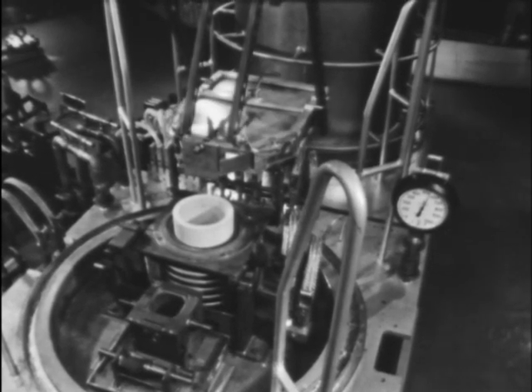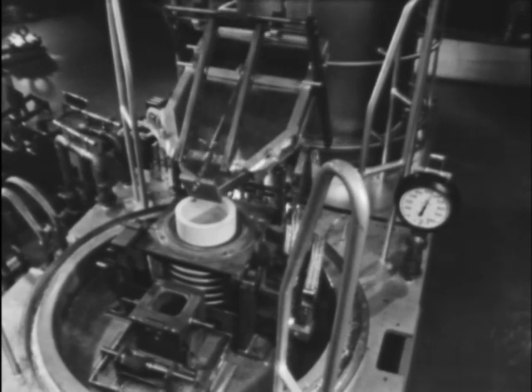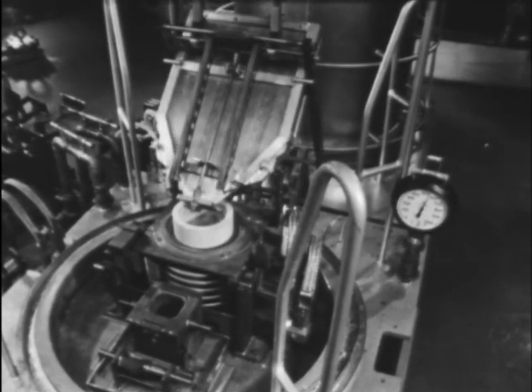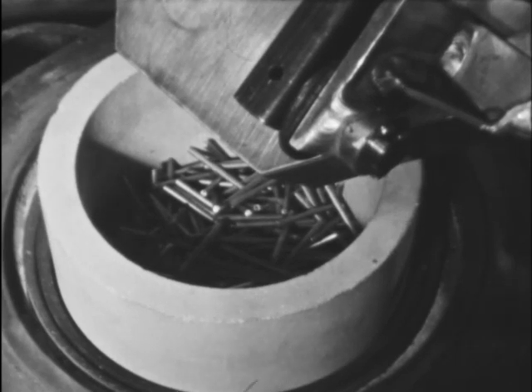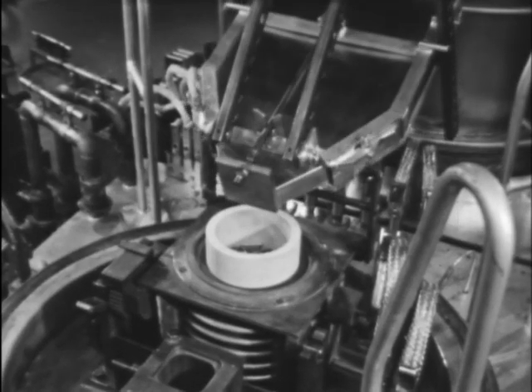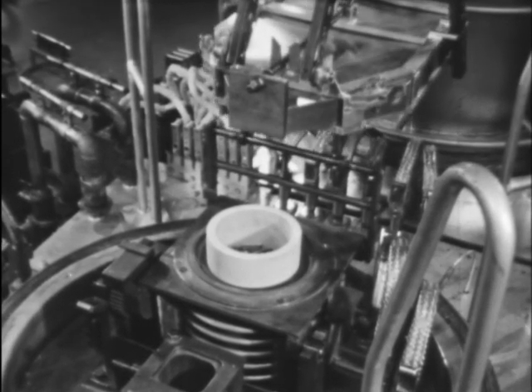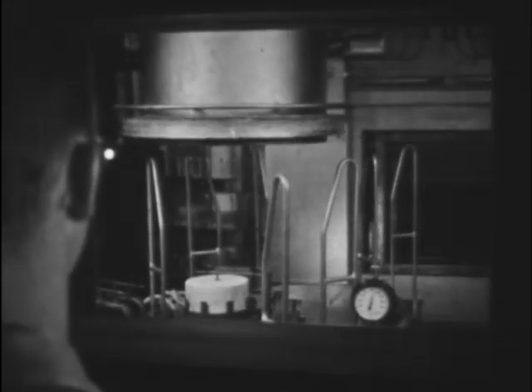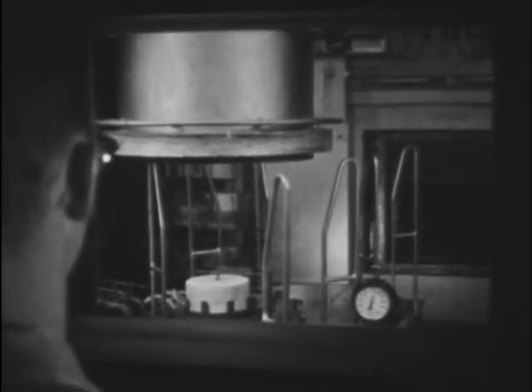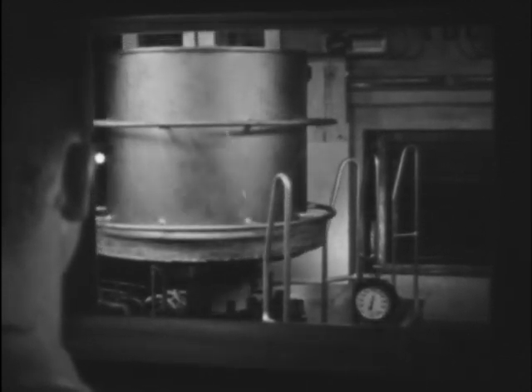This irradiated fuel is next purified by melt refining in a zirconium oxide crucible. Required additions of fuel to replace that consumed in power operation are charged in the melt refining step. Condensable volatile fission products are absorbed in the fume trap, while other fission products are removed by selective oxidation.